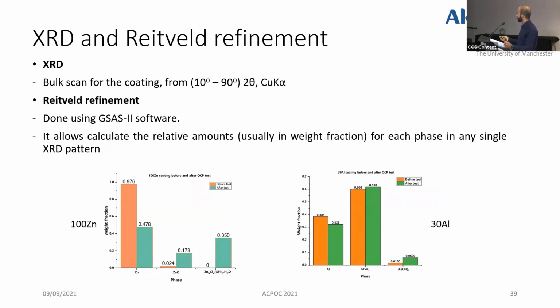The XRD and Rietveld refinement were done by bulk scanning of the coating from 10 to 90 degrees, and the Rietveld refinement was done using GSAS-II software, and this software allows you to calculate the relative amounts, usually in weight fraction, for each phase in any single XRD pattern. So for 100 zinc, after the electrochemical test, the only corrosion products are zinc oxide and simonkolleite, which is zinc chloride hydroxide.